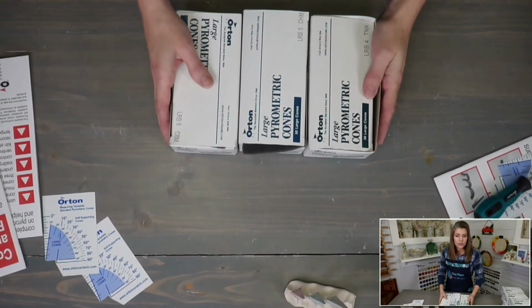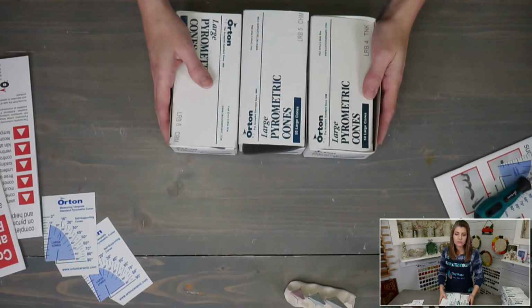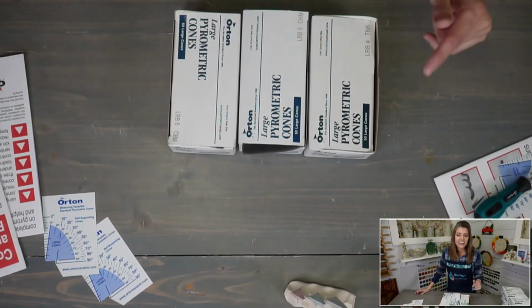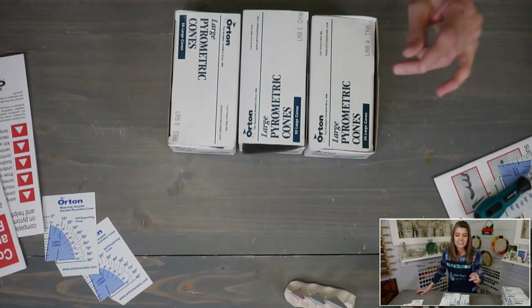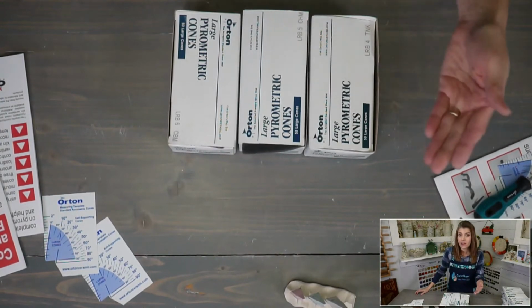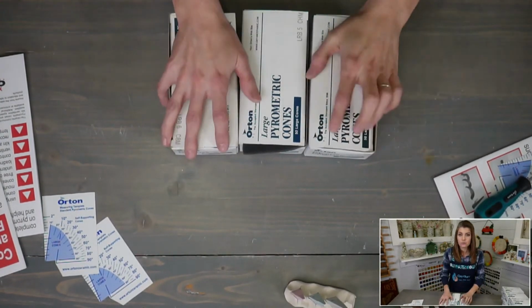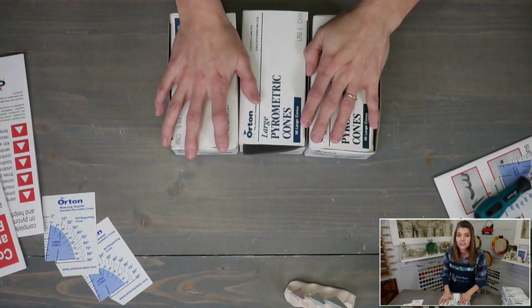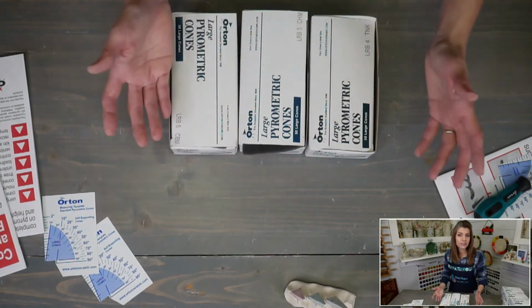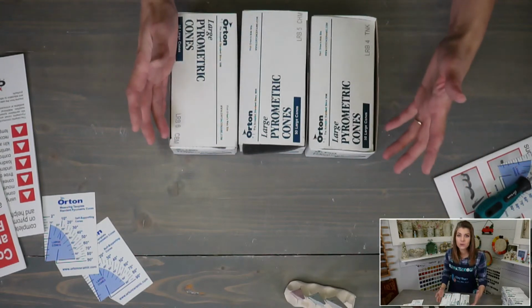The cone pack showed cone 4 laid flat, cone 5 bent over, the cone 6 just moved. So, Sharon, interestingly enough, that's where your pyrometer that's reading it out is not giving you the heat work. You got to cone 5. You actually got to cone 5. Are you happy with the glaze results? Did it turn out the way you want?